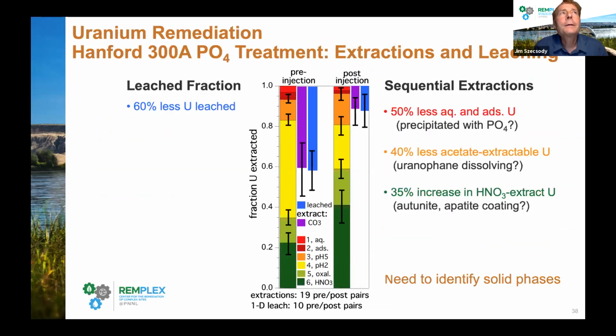And this slide is a little bit underwhelming, but this is actually a summary of all of the results of the phosphate treatment. So we actually have 20 or so pre-post pairs of 1D leach experiments, like the one I just showed you. And in the pre-injection, about 40% of the uranium leached out of that sediment. But 6 months after the field scale treatment, core holes were drilled, about 3 feet away from where those pre-injection samples were taken, at the same depth, and in those sediments, about 1/3 of the uranium leached out, so about 13% of the uranium leached out.